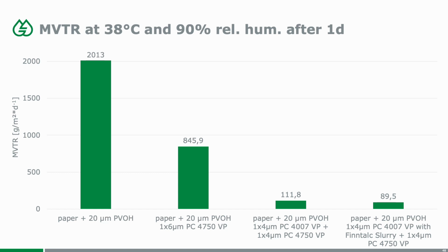So that's where proper MVTR starts, and then you can make it even a little bit better if you use some fine talc in the PC4007 primer and then recoat it with a 4750. That is where the talc gives you additional barrier properties thanks to its lamellar structure.